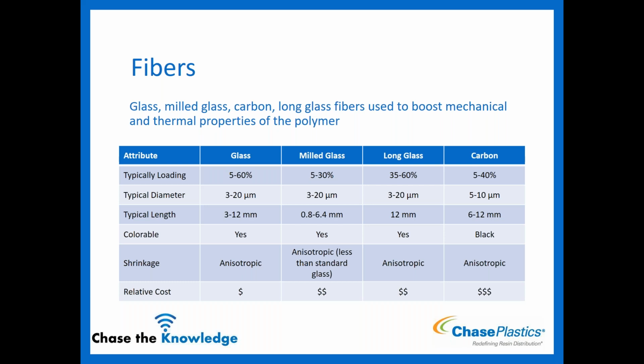And then lastly, we have carbon fibers. So you typically see that in the 5 to 40% range. The one thing to note here is because of the color of the carbon fiber, it is difficult to do it in certain colors. So typically we just sell the material in black because it's easier that way, because it's already kind of a grayish, blackish color. It makes it easiest. It is a little bit more expensive. The other thing that's unique about the carbon fiber is that it will impart some level of conductivity. And so that's another value if you're looking at certain materials, maybe an ESD range for performance or properties, something that could be looked at as well.